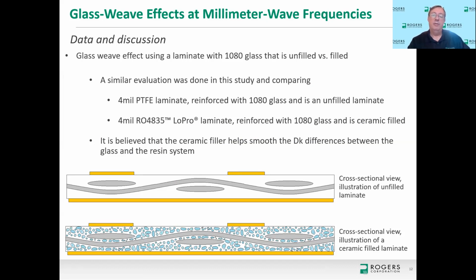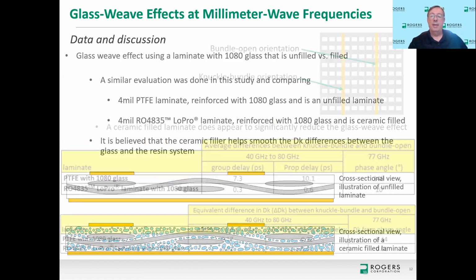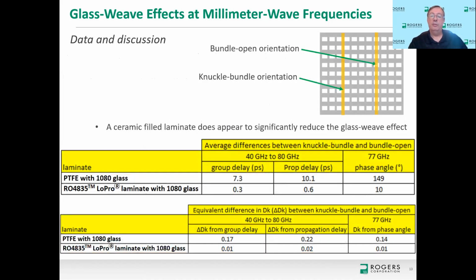And in theory, we've always kind of thought that the ceramic particles would be an intermediary between the Dk of the glass and the Dk of the resin system to kind of smooth out that effect to really minimize the glass weave effect. And that's really why we did the study. And sure enough, that's exactly what the data showed.